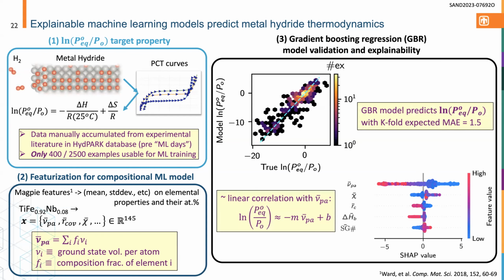If you just train your simple gradient boosting tree model off the shelf, it can actually produce this log equilibrium pressure with reasonable accuracy. Sometimes I'll mention it as delta G, because the equilibrium pressure is essentially delta G. You can predict that log value to within around 1.5. So it's pretty decent at correlating metal hydride stability across the wide ranges that these materials can exist.